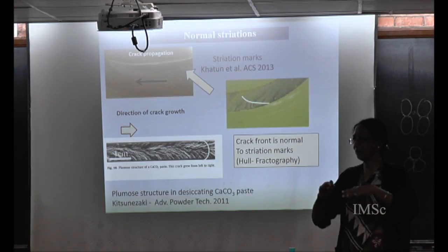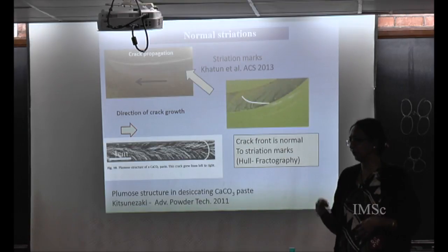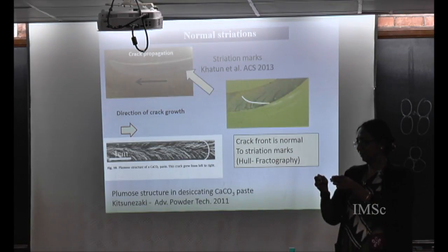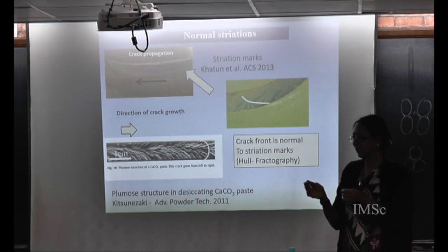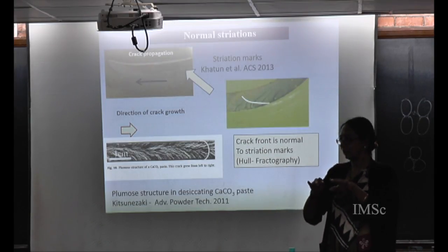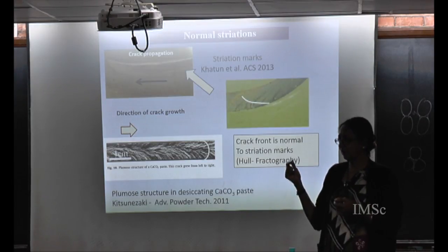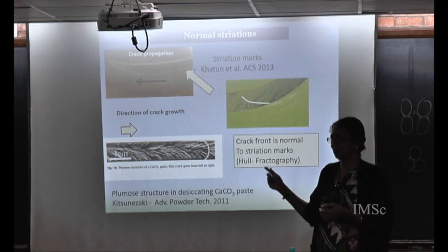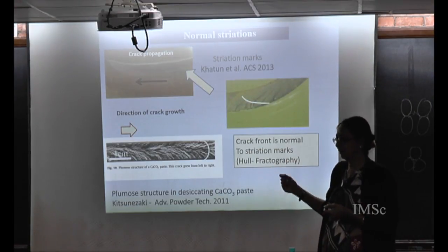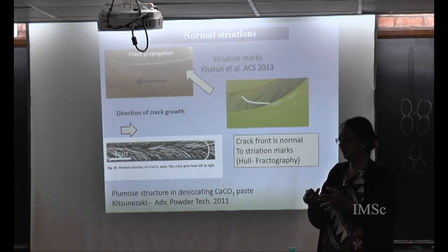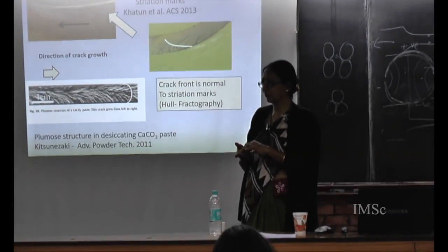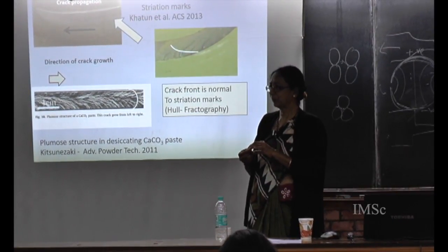Is it? Yes, because we are saying that this is mixed mode, it is bending. Well, no, the experiments I was talking about now are mode 1 experiments. Yeah, but we haven't done mode 1 actually. We are bending it, rather like that 3-point loading experiment. So we are trying to correlate with the drying case, but the drying case is not really mode 1. Yeah, you have several modes. But if you see the speed of your front, you can try to see if when it goes slowly, it leaves a mark, and when it goes fast, it doesn't.